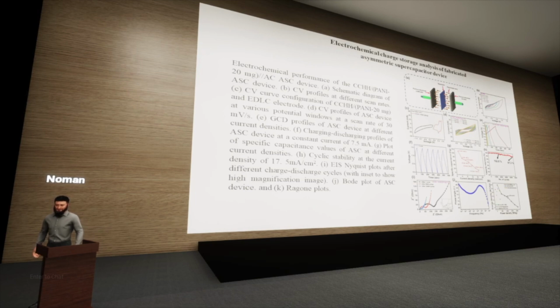This is the cyclic voltammetry in the negative potential of the activated carbon, and this is the CV curve of the material that shows the maximum results. And after performing these tests and optimizing the potential window of the device, we performed cyclic voltammetry at various scan rates, galvanostatic charge discharge at various current densities, and continuous cycling, and the capacity retention with respect to current rates and stability. Our device shows very good stability up to 97.2% after 5,000 galvanostatic charging discharging cycles.